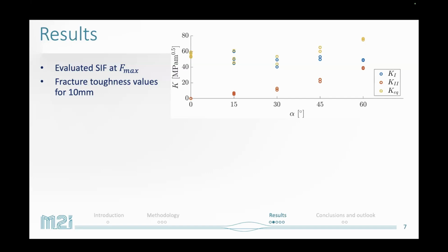And we have the K equivalent. Initially, before we started this research, I thought that evaluating this based on K equivalent would result in the best fit. But if you look now, this yellow line is the average of the K equivalent, and the dashed lines are plus and minus 1 times the standard deviation.